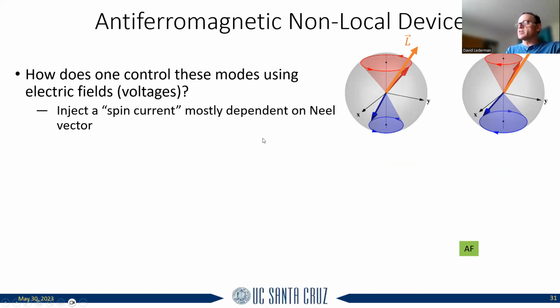So what you would do is inject a spin current, mostly dependent on what's called the Néel vector. The Néel vector is M1 minus M2. So the sublattice magnetizations are these vectors, and you notice they almost point in opposite directions. This is L. This is not angular momentum, by the way. L here is the Néel vector, M1 minus M2, which I've drawn here for this case and here for this case, so they're slightly different for the two modes. The spin current you can generate goes as L cross dL/dt, because if you have an interface and this is precessing and encounters the interface, it's going to look a lot like it does for a ferromagnet, except now it's the Néel vector that matters.